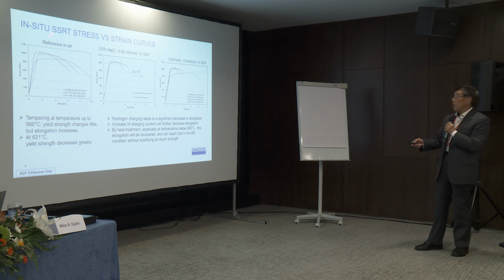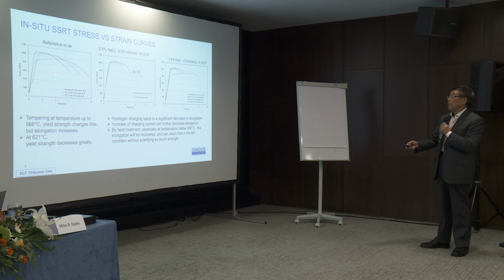First, this curve shows what I call the reference without hydrogen charging. We can see this is as-received. Here is tempered. With tempering, the elongation increases, and increases with temperature. Then this is after hydrogen charging, but here only the current is 0.05. For this as-received material, the elongation is significantly decreased from about 9.9 to about 3. But interestingly, with tempering, the elongation increases.